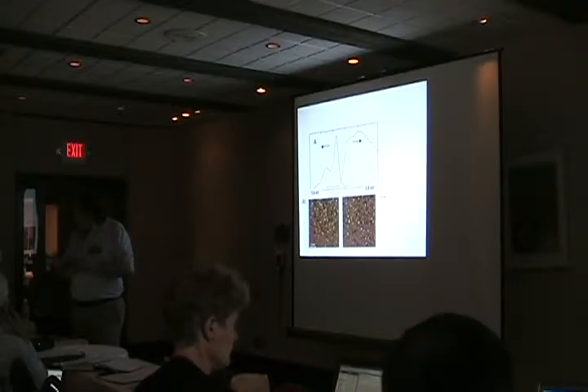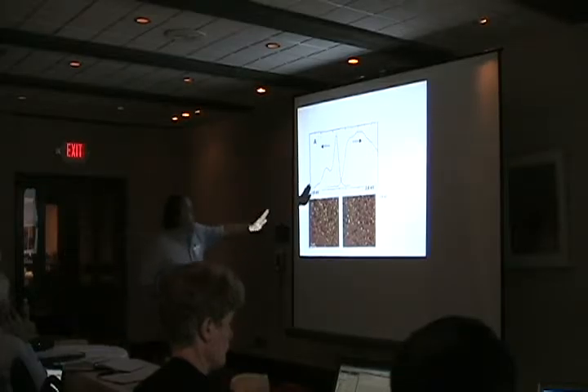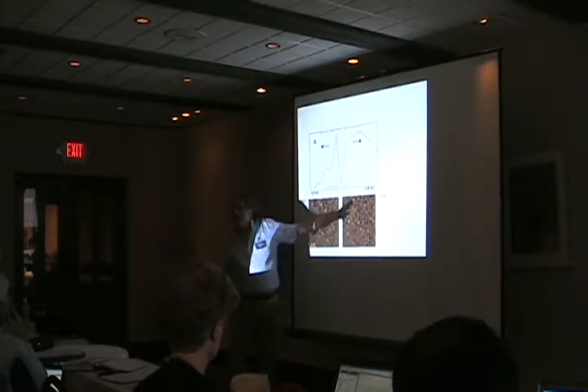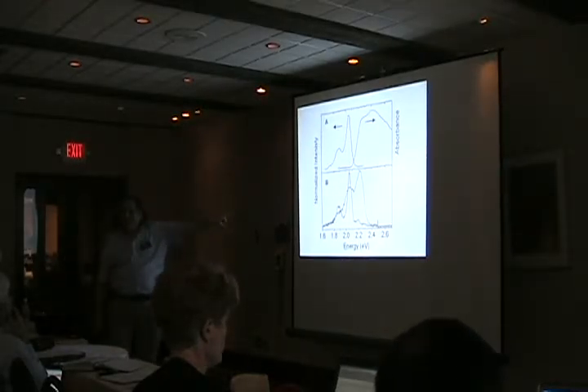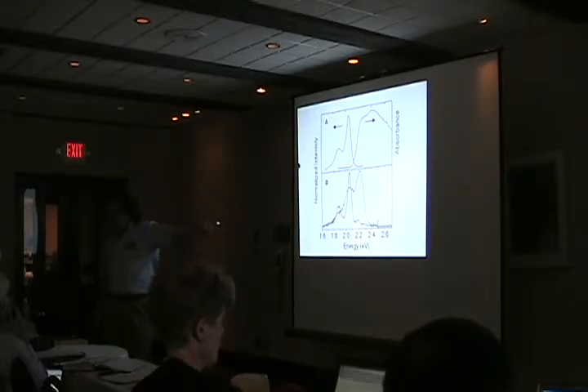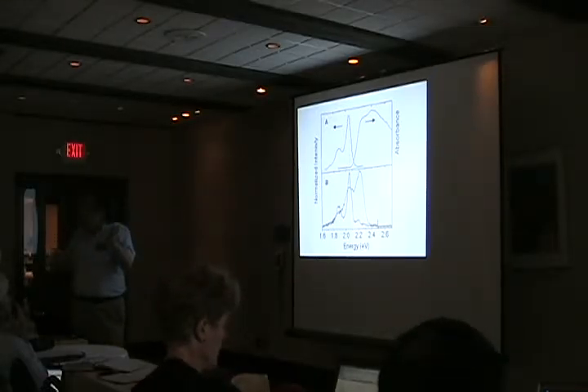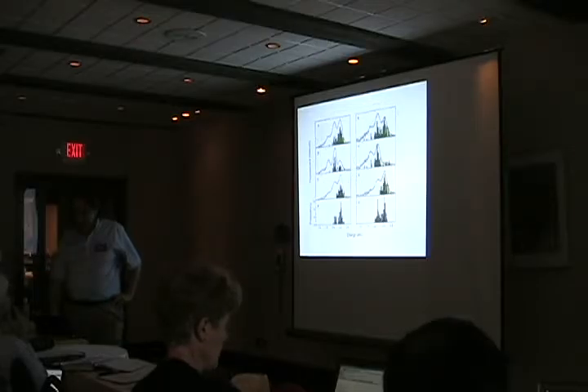This is what's used in all the devices, and this was never really driven home until we did the experiments and showed that if the polymer chains are short enough, the probability of having one of these acceptor sites is very small. The emission now moves to the higher energy, in resonance with the absorption, because you've interrupted energy transfer. And there it is. There's the emission that would be there if you could cut off energy transfer. So the Stokes shift is from energy transfer, and the acceptor sites are due to folding of the polymer chains.